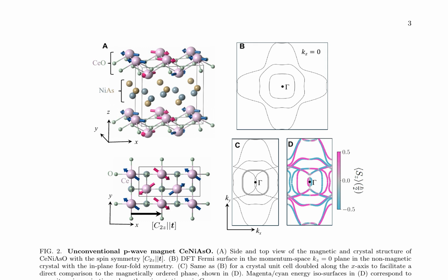The authors calculate the band structure using the Vienna Ab initio Simulation Package, VASP, with the Perdew-Burke-Ernzerhof, PBE, exchange correlation functionals, constrained noncollinear magnetism, and symmetrization switched off, in the non-relativistic limit. The results display a linear band crossing around the gamma point and a spin polarization in momentum space perpendicular to the direct space exchange fields.